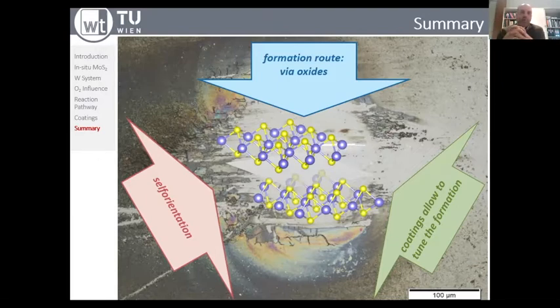And the final point that I could show you by the TEM investigation is that you need a kind of self-orientation of these partially crystalline forming fragments in the tribofilm that are then subjected to shearing, so that you have all this coming together to make it work.